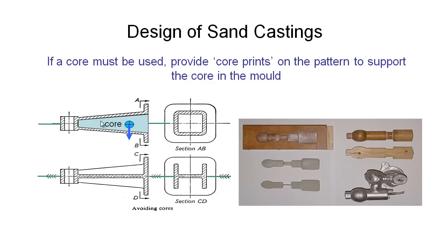Unfortunately, if we just stick a core in there loosely, then there's nothing to hold that core in the center of this cross section, so it's just going to fall down and sit at the bottom of our cavity, which is not what we want. We're not going to get the part that we've designed. And so we need some way of supporting this core in the right position and making sure it doesn't move. And to do that, we would need to add a considerably large core extension, which will support the core within the sand and then allow the bit that's going into the part to be cantilevered out into space before we actually pour the metal in there. So if we do that, it's now supported by the sand over here. And we've also moved the center of gravity of this core over to where it's actually got some support, and so it's less likely to move around and even break off or fall in there.